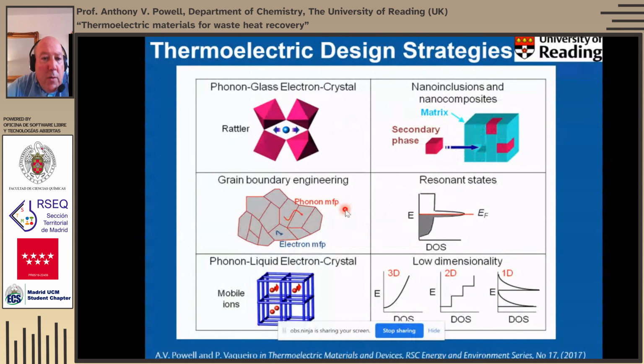It's also possible to do some microstructural engineering. This is something I won't be speaking about today, but you can do grain boundary engineering to effectively scatter phonons selectively compared to scattering electrons. Phonons typically have a longer mean free path than electrons do, so therefore you can actually design your grain boundaries to impede the propagation of phonons without necessarily affecting the electron transport.